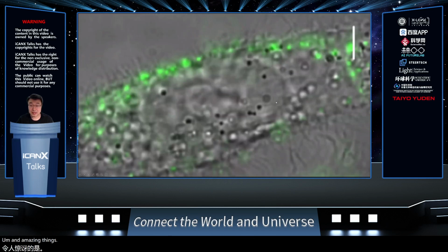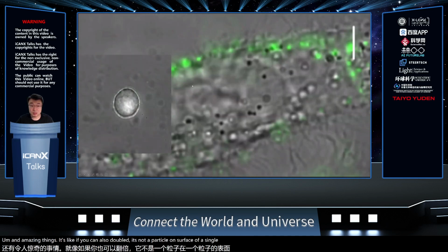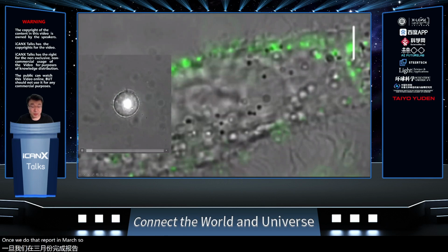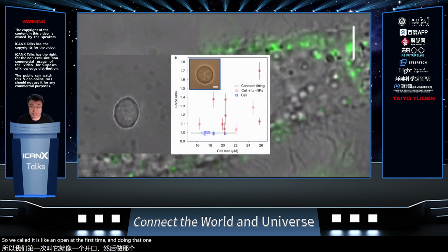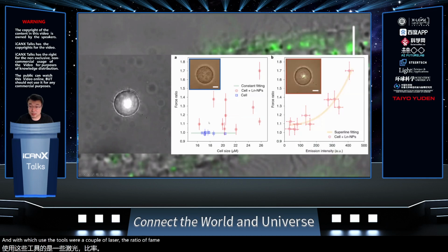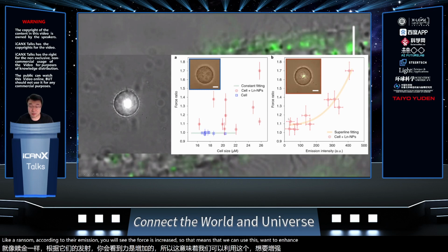The amazing thing is we can also dope these nanoparticles onto the surface of a single cell. We put the nanoparticles on the surface of the cell, and doing that, we can enhance the force interaction. We call this the force dye. For the normal cell, we use two different colors of laser and the ratio is the same. But for the cell doped with nanoparticles, shown with this red circle, you will see it is a little bit random. But if you arrange them according to their emission, you will see the force is increased. It means we can use this to enhance the force on the biosample.